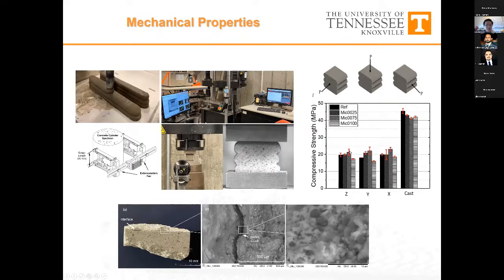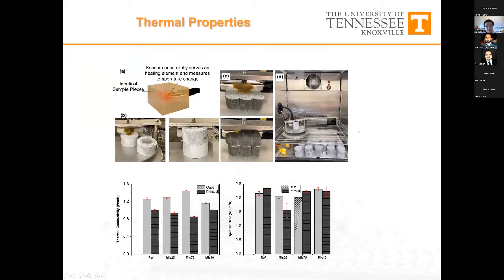Again, I think that because of this higher porosity that we observed in the printed sample, we have seen a pretty drastic drop of the compressive stress. We tested further the thermal properties. I'm going to skip that because nothing too intriguing that we see here.